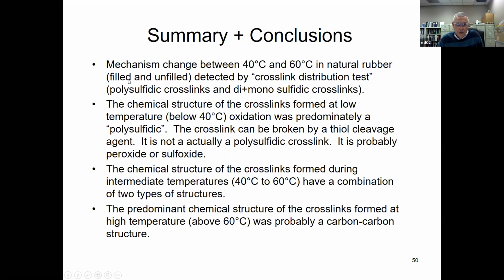We used both filled and unfilled compounds. And this was detected only by the crosslink distribution test, polysulfidic crosslinks and di- and monosulfidic crosslink formation rate.